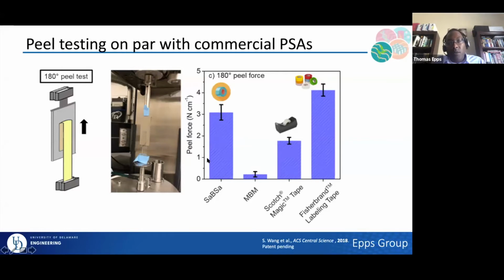And so one of the things that we can do then is we can do that peel force, 180-degree peel force study. You can look at our material, our block copolymer. You can compare it to that base MBM. So you might say, well, what is this comparison? But basically what I do is I take a base like MBM, I add a bunch of tackifier, other additives, and that's how I get things like my Scotch tape and my Fisher brand labeling tape.